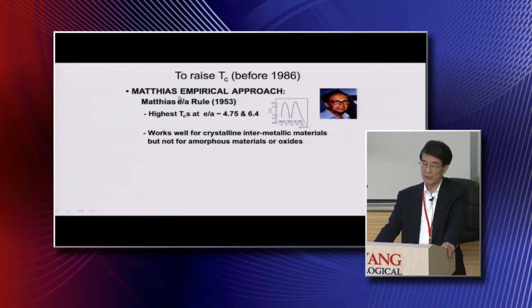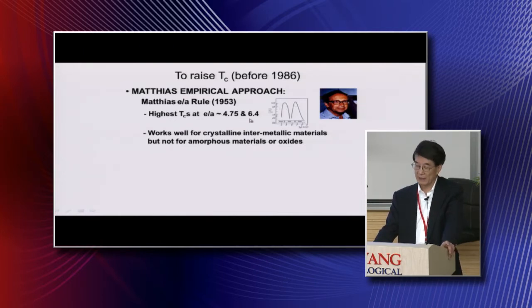The first, we call it Matthias' empirical approach. Basically, he just looked at the valence electrons per atom. And he found out the highest TC usually occurs in two places. One is 4.75, and the other is 6.4, so two peaks. That means when you have those electron counts per atom, it doesn't guarantee a higher TC, but the highest TC occurs at these two numbers. It works well for crystalline intermetallic materials, but does not work for amorphous materials nor oxides.